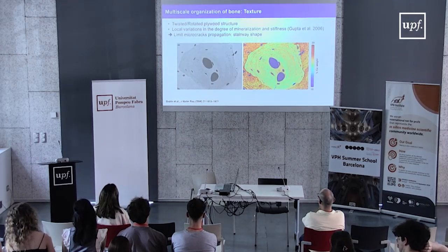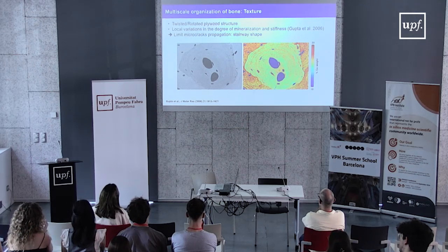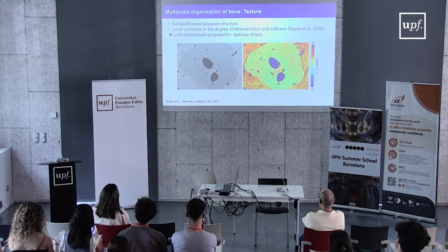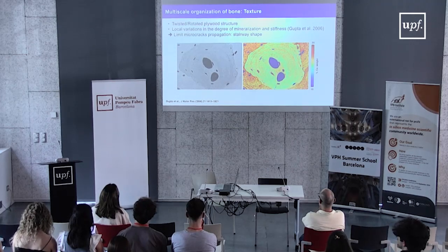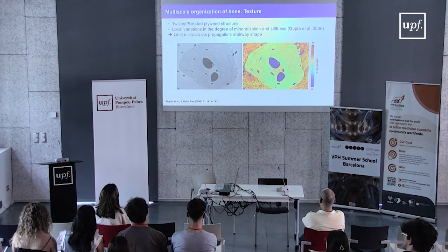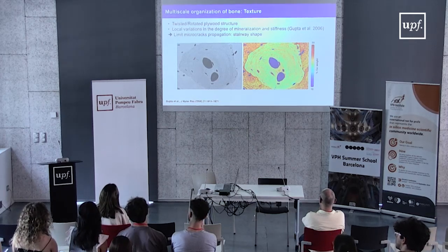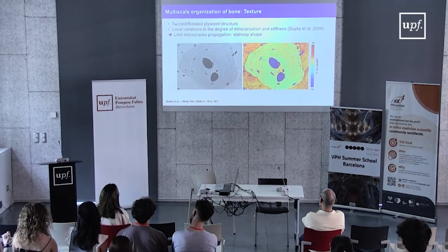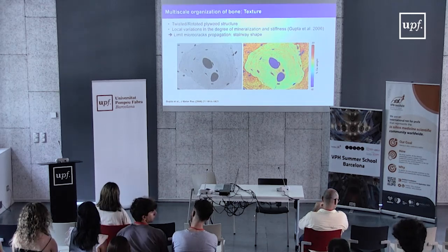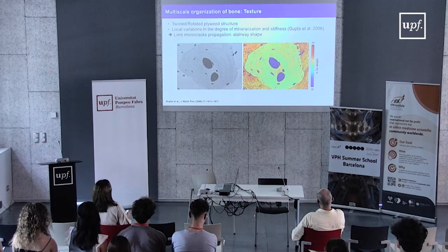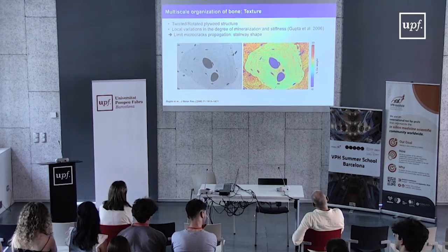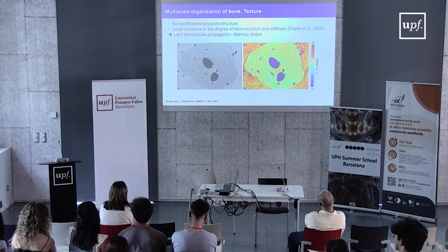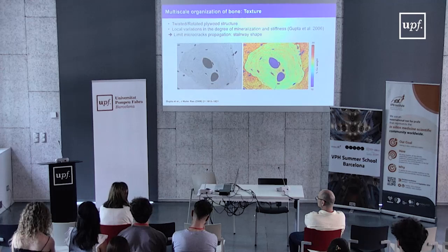This cholesteric structure is also important for the pattern of mineralization of your bone matrix. If we look, by qBEI, quantitative backscattered electron imaging, at the amount of mineral that is incorporated into the bone matrix, here we're in cortical bone, where we have what we call an osteon, which is a compact structure of the bone, like a column of bone matrix. When we look at the arrangement and the degree of mineralization of the different structures, you will see zones which are highly mineralized, which appear quite red, and zones which are low in mineralization degrees that appear more greenish.